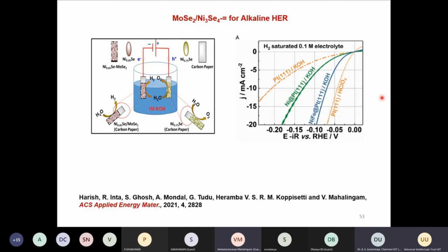Acidic OER is again a very challenging thing. And also in the alkaline part, if you see OER, we have different materials, but getting the hydrogen evolution reaction in alkaline OH- is again a bit challenging. The reason you can see, for example, is platinum, which is a very good catalyst, which I mentioned before, is very good in HClO4, in the acidic medium. If you change to KOH, you see the activity decreases very much for the platinum 111 surface, which is a very good catalyst for hydrogen evolution in the acidic medium. But when we come to the base, the hydroxide or alkaline medium, it's not a very good catalyst.